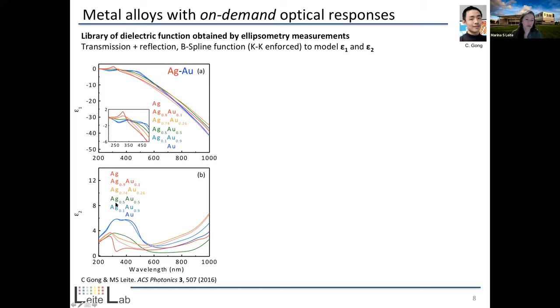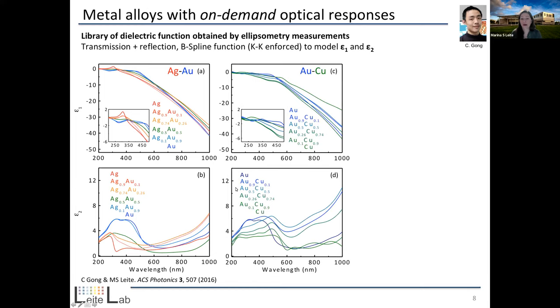So for example, for a mixture that has 50% of silver and gold, we did see that the imaginary part of the permittivity, epsilon 2, actually achieves a minimum here that is below the one for the pure counterparts in the near infrared. So that can be very useful again to design a certain photonic device where we want very little light absorption. I mean, you want to minimize epsilon 2. It could be in a different situation now where, for example, we want to have a lot of light being absorbed by the material. So for example, when we design a super absorber, and I'll show an example of that in a few slides, then we actually want a really high epsilon 2.